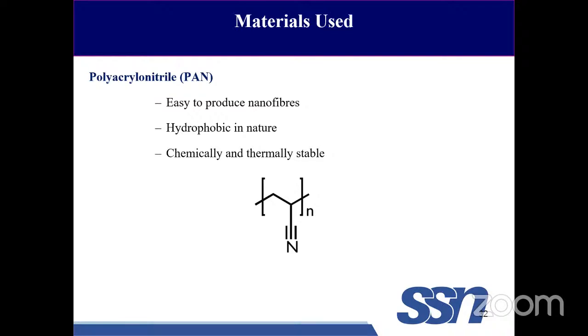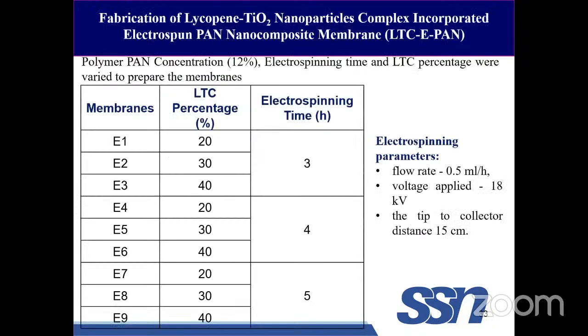So we have the lycopene-incorporated TiO2 PAN, and we prepared 9 photocatalytic membranes out of it, with different dopings of TiO2. That is 20, 30, and 40, and we varied the electrospinning time: 3 hours, 4 hours, and 5 hours. So these are the electrospinning parameters that we utilized. Totally 9 samples have been prepared. We named them E1 to E9.